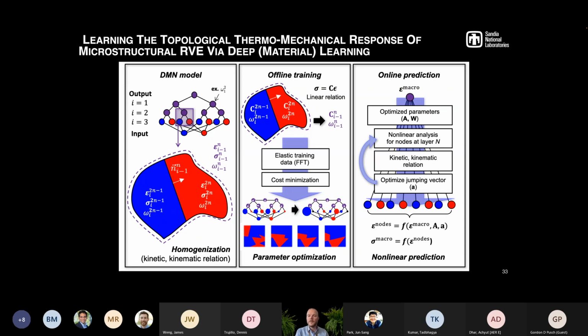This architecture is a little bit specific, and it's physics informed because the operations done at the neural level are based on classical micromechanics and homogenization rules. So you can define a relationship between the macro stress and the local stress. You can define a relationship between the macro strain and the local strains. You can define a relationship based on the Hill-Mandel principle that gives you the equivalence between macroscopic conservation of energy and what you would get from your local fields, and so on. And so instead of having classical operations such as multiplication, division, subtraction, etc., done at the neural level, now you're using micromechanics rules to pass the information.